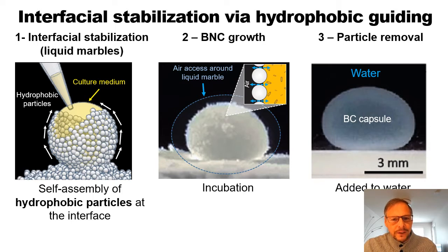Then if we wait for some time, after some incubation, the culture medium inside that contains the microorganisms will undergo the production of the cellulose by the microorganisms, and that cellulose will grow close to the hydrophobic particles. So at the end, what we will end up having is a capsule of bacterial cellulose after removal of the hydrophobic particles. So what you see on the far right is actually a cellulose network that forms a capsule in three dimensions, like a sphere, and is fully cohesive.